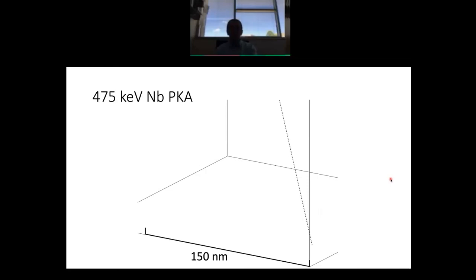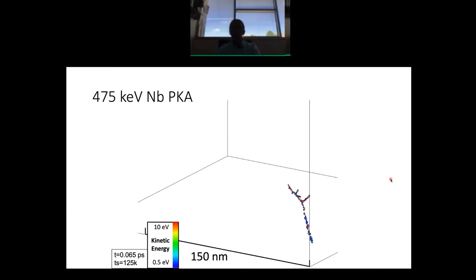Now, what Richard did is he initiated a primary knock-on atom, a niobium primary knock-on atom, at an energy of 475 kiloelectron volts. And here's what he saw. Here we're coloring atoms by their kinetic energy. You're seeing all the atoms whose kinetic energy is 0.5 electron volts or above, colored on a scale that goes from 0.5 to 10 electron volts.